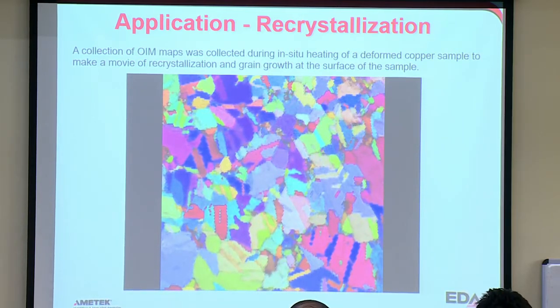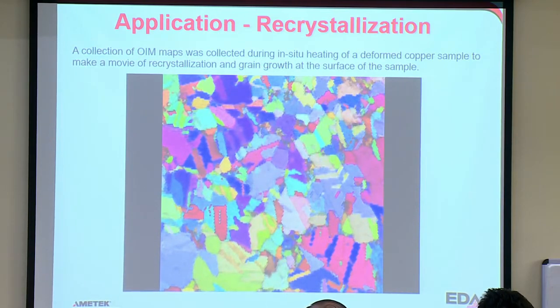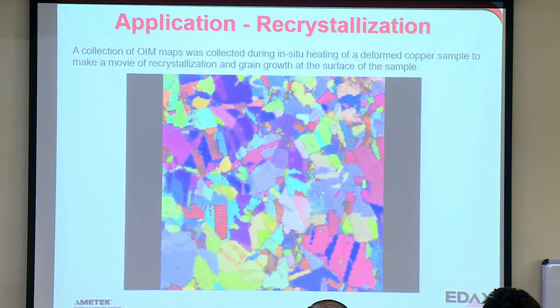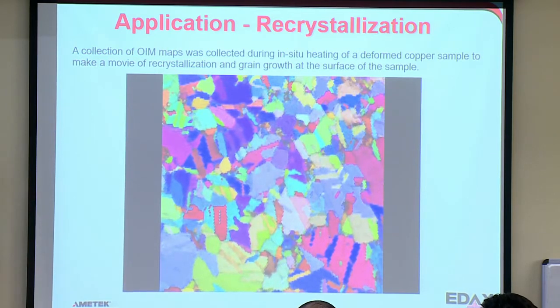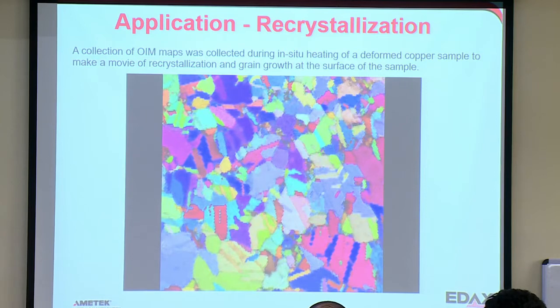And so in this study we were trying to understand why some grains would start recrystallizing more quickly. It's both a nucleation effect, but also an orientation effect. And some of those grains are either oriented in such a way that nuclei can't form, or there's not quite enough deformation to have the driving force for that recrystallization.